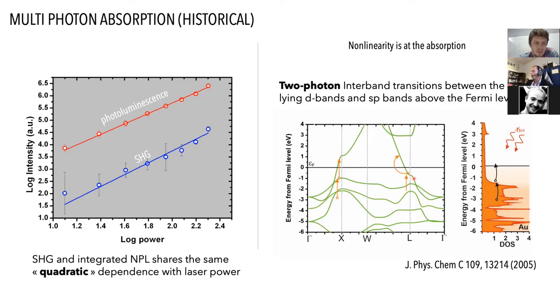Here you will see the density of states for the electrons. And you will see that again, there's a lot of electrons lying at a few eV down from the Fermi edge. And since we are using a laser at 1.7 eV, one photon is not enough. So you need to have two photons in order to bring an electron from the D band to the sp band. And this was for a long time the accepted interpretation of this nonlinear photoluminescence.